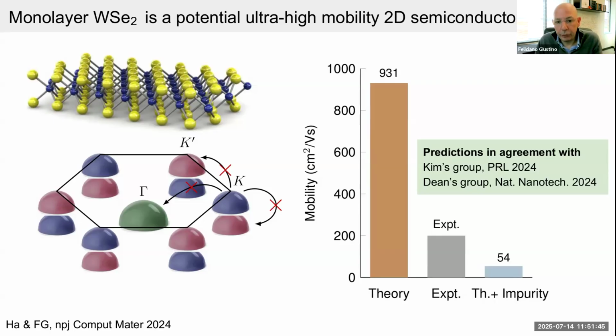If it comes to functional properties, for example, transport or optics, that's more challenging because usually these calculations are 1 or 2 orders of magnitude more expensive than plain DFT. For example, if you want to study the interface between these dichalcogenides with an insulating substrate like hBN, that can be challenging because hBN has a smaller lattice parameter, so you will need a supercell which has maybe 4x4 unit cells of those, and then you already run into something of the order of 50 atoms, which for standard DFT is trivial, but for advanced transport calculations is very expensive. So usually what happens is that we discuss with experimentalists and then we tailor the approach to the question. The more complex the property you want to calculate, the smaller the system size you can afford. That's the trade-off.